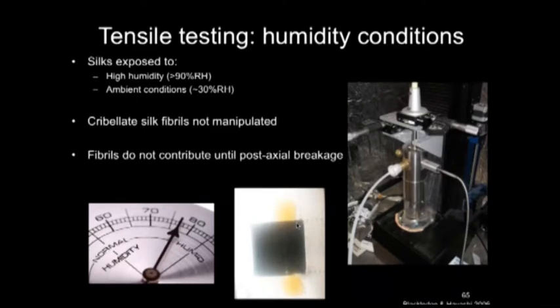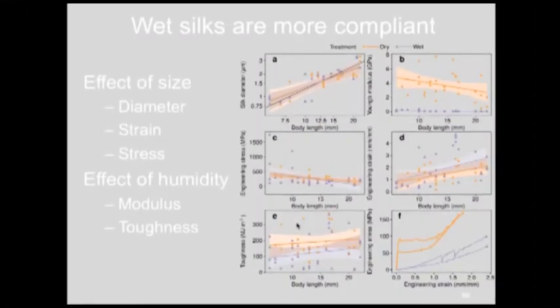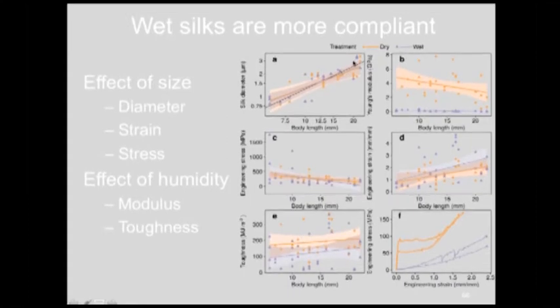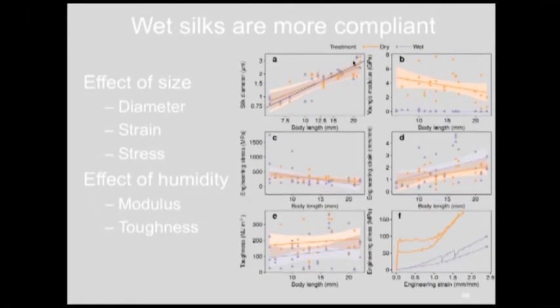So from that, we were able to see a lot of interesting things. We compared across body size because, again, these spiders live in all sizes together. So we compared these properties between two different treatments of dry and wet across body size, similar to what we did previously with dragline silk. We found that diameter increases, again, not differently from what we'd expect from isometry, meaning that there's no particularly interesting changes in diameter of the silk compared to the size of the spider. And then we see changes in stress, meaning the strength. It actually gets slightly weaker as spiders age, and the extensibility increases across age, meaning that toughness is about the same, the overall energy.